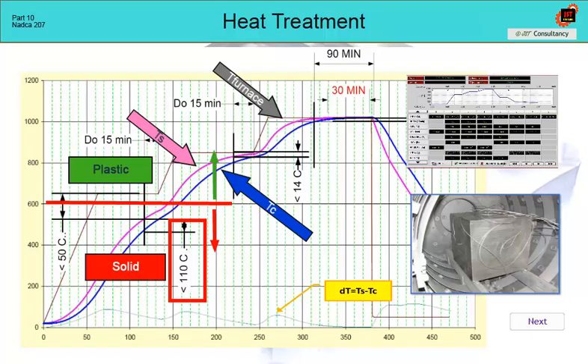The control system of the furnace must therefore be able to react not only to changes in the temperature of the furnace, but also to exceeding the temperature difference between Ts and Tc and slow down the heating to the permissible limit. In practice, this is usually solved by stopping the heating ramp and inserting an extraordinary hold in the heating period, when the furnace waits for the temperature difference between Ts and Tc to decrease.